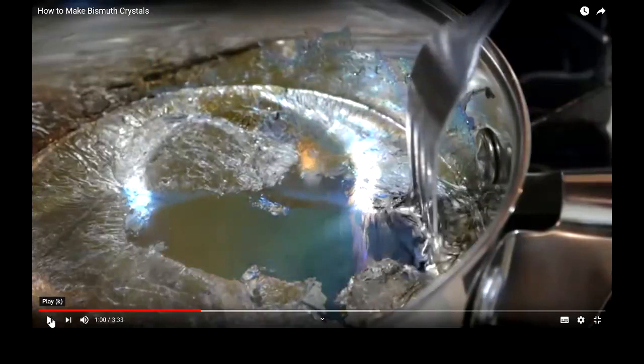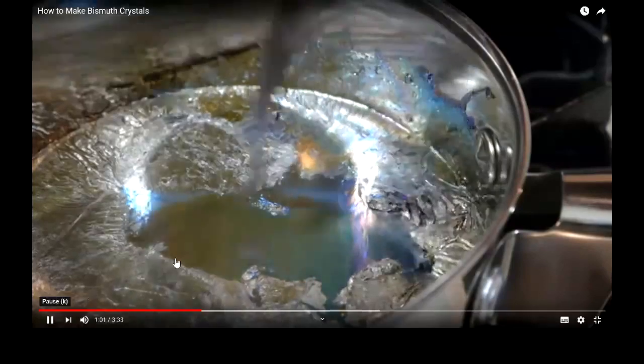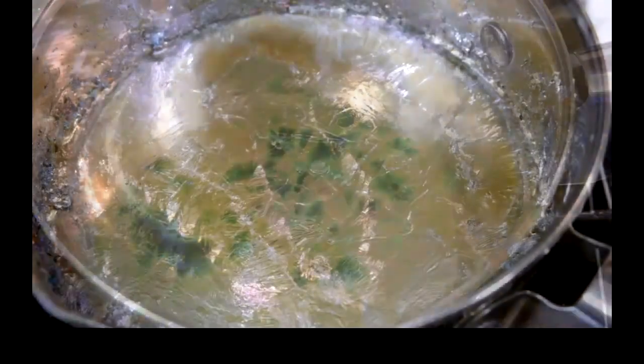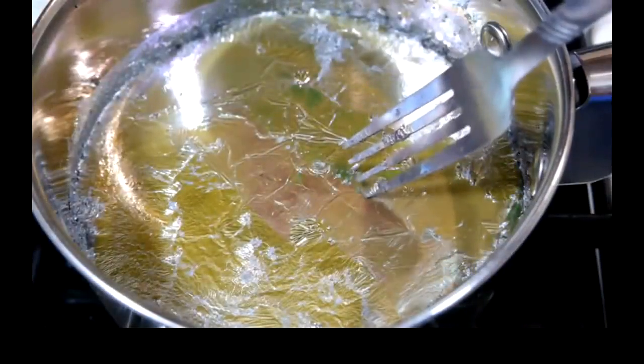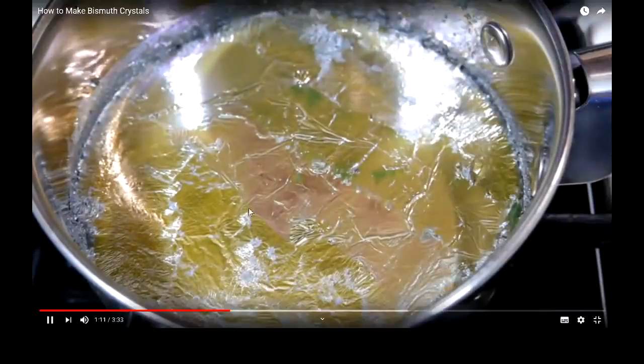So we've melted a liquid here, and you can see what I call a decent oxide scale on top. Typically when a metal reacts with oxygen, the oxide that forms is going to be lighter than the metal itself, so it will always float to the top. That's important as we move through the video. Contaminants will float to the top, where they can be skimmed off. As the temperature falls below bismuth's freezing point, crystals begin forming at the surface, growing downward into the molten metal beneath.